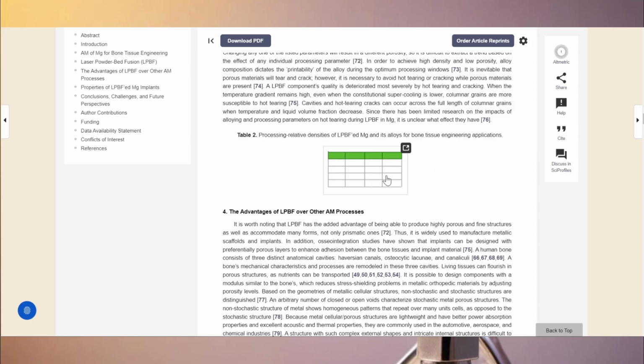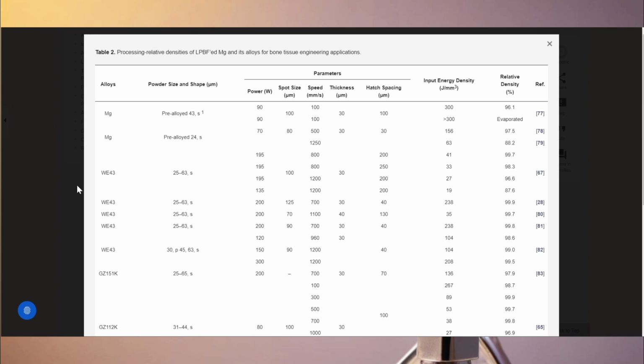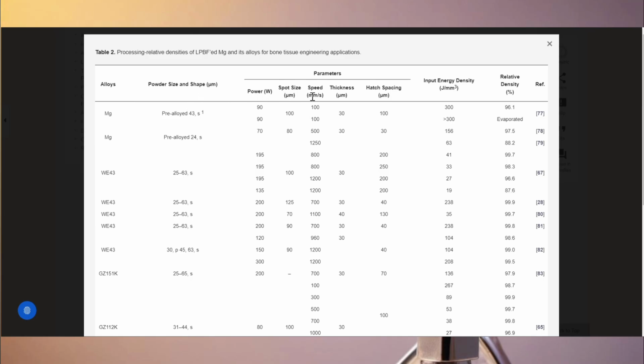And let's talk a little about Table 2. This table showcases different magnesium alloys like pure Mg, WE43, GZ151K, and GZ112K. They all are being processed under various laser power settings, scanning speeds, and layer thicknesses. Each set of parameters leads to a specific energy density, which in turn influences the final relative density of the printed part. You'll notice some combinations result in densities above 99%, while others dip below 90%. So in essence, the table underscores how even small changes in processing conditions can drastically affect the quality of magnesium-based implants, whether that means higher densities, fewer pores, or better mechanical performance.